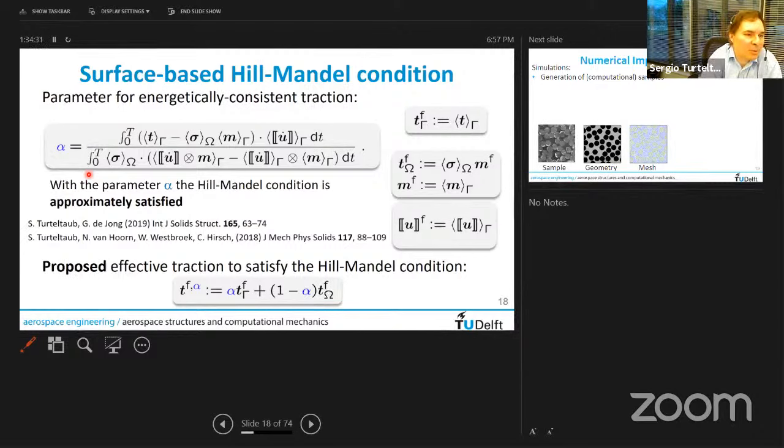And in fact, I'll tell you, we tried a few things. Of course, embedded cohesive elements everywhere is not the most clean approach. So I'm the first one to recognize that it's a quick and dirty type of way of doing things. Part of the issue is that when we try other methods, so we tried XFEM as well, but with XFEM, when you have intersecting cracks, it becomes an issue. So for complex crack patterns, which is what we end up having everywhere, the embedded cohesive element approach seemed to be much more robust to handle intersections of cracks.